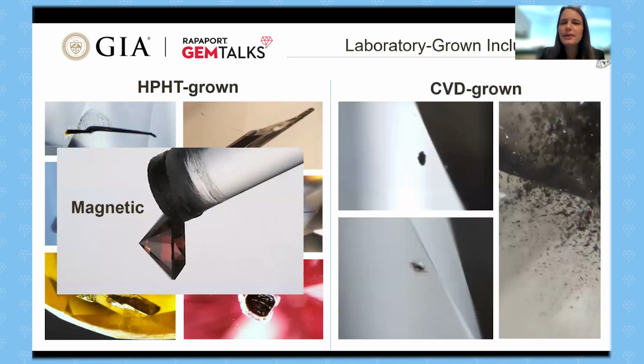For the CVD grown, though, it gets a little bit more complicated. You see, most of the material that's trapped in there is essentially just carbon that didn't quite bond properly. So you have essentially graphitic material or non-diamond carbon materials inside. Sometimes if these diamonds have been HPHT processed to decolorize them, you might get a little bit of a stress halo surrounding one of these. But really, these inclusions are very similar to what you might potentially see in a natural diamond as well, so they're not particularly diagnostic.